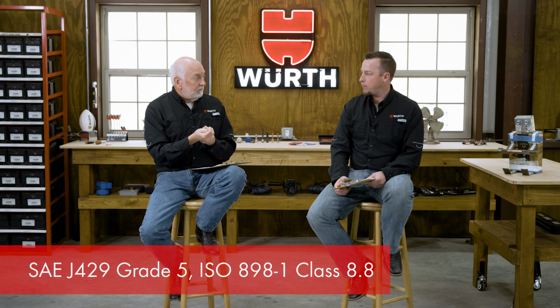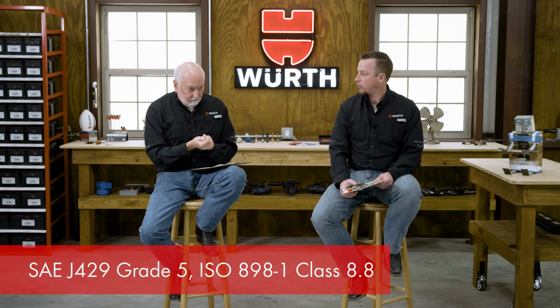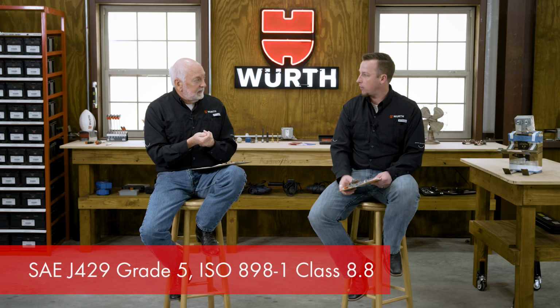So we look at a Rockwell C scale, and at a Rockwell C scale of about HRC 34, right, that's an SAE grade 5 or ISO 898 class 8.8. Correct. That range right there. Yep, in your fastener strength categories, they're soft, they're ductile, they're taffy-like, they're soft candy-like. Okay, now because the hydrogen still goes there. It does. But we say that material, and the word we use, it's not susceptible. So it is soft and ductile-like.